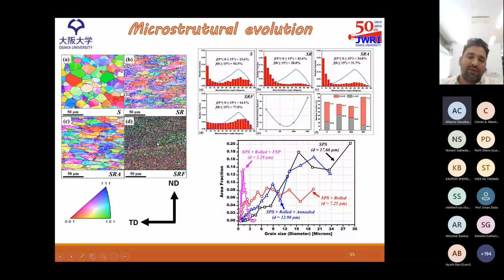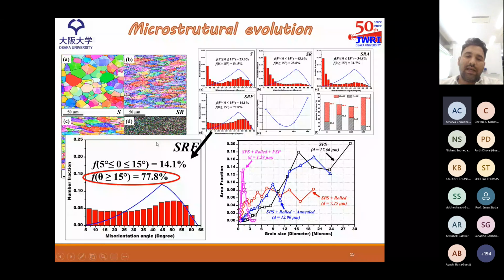However, the most interesting thing is that it has more than 77% high angle grain boundaries. It means these fine structures are not subgrains. Instead, they are grains. So we can say with surety that there is a mechanism like discontinuous dynamic recrystallization for the formation of these fine grains.